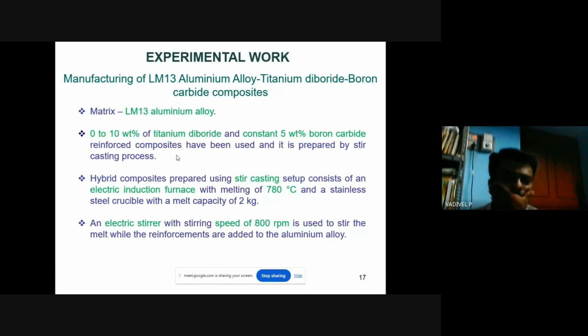So here we come to the experimental work. How the manufacturing of this LM13 aluminum alloy, boron carbide, titanium diboride is done. First of all, we had the aluminum alloy matrix, and then the weight percentage of titanium diboride is varied from 0 to 10 weight percent, with a constant 5 percent of boron carbide kept, and the composite has been prepared by using the stir casting process. Here we have varied the percentage of titanium diboride from 0 to 10, and we had a constant 5 percent by weight of the boron carbide for this process.